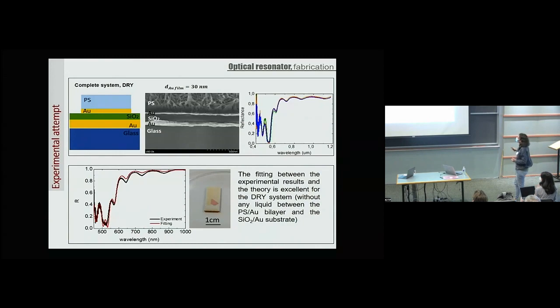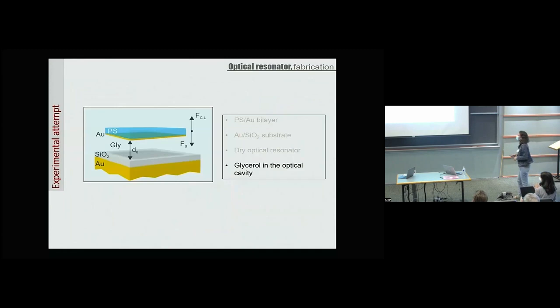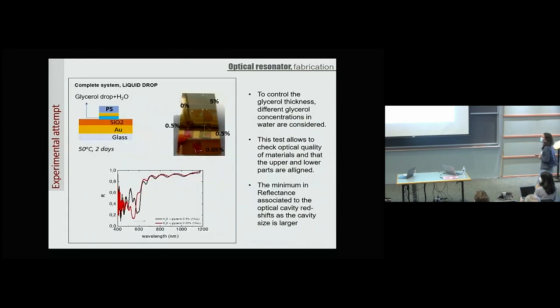This is the reflectance spectrum in different positions of the sample, and we have this minimum here of the optical cavity, and then some oscillations related to the polystyrene film. The fitting with the theory was excellent, so we knew the exact thickness of the layers, and we put this into our transfer matrix code, and everything was fine. This is how it looks. Also, we can see this optical cavity. But then we tried to include the glycerol, and when we did this, we had some problems.